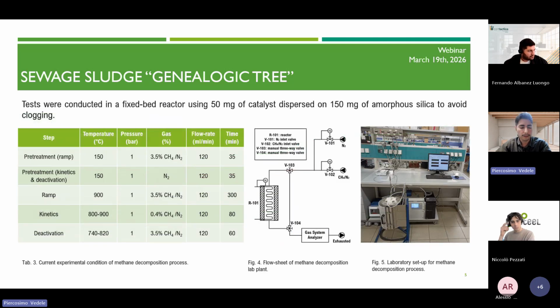But let's go deeper into the test phase. On the right, you can see the lab test bench that we use for conducting our tests. All the tests were conducted in a fixed bed using a fixed amount of catalyst and a fixed amount of an inert, an amorphous silica, to avoid clogging of the reactor caused by the carbon deposition. We can conduct three different kinds of tests: a ramp test to evaluate the best of the 5 biochars that we are considering, so to make a screening of the biochars, and kinetic and deactivation tests to get the kinetic and the deactivation parameters. All the tests were preceded by a pretreatment phase in order to ensure the dehumidification of the catalyst.